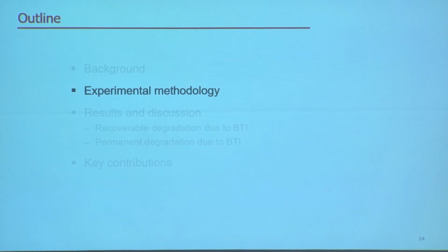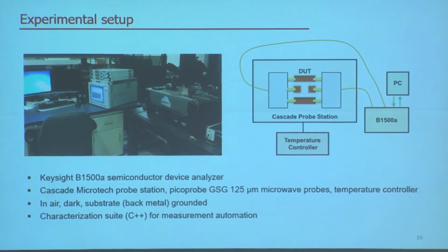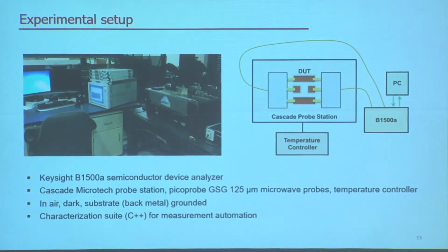Okay, next I'll talk about our experimental methodology. First, the experimental setup. This is our lab, the setup for all the experimental work I've done, on the 3rd floor. We use a Keysight B1500A semiconductor device analyzer connected to a Cascade probe station. We use an RF probe tip, GSG 125 micrometer. And the chuck is connected to a temperature controller, which you can see in the picture behind the station, and it helps us do all the temperature measurements. All the measurements are done in air and in a dark chamber, and the substrate is grounded.